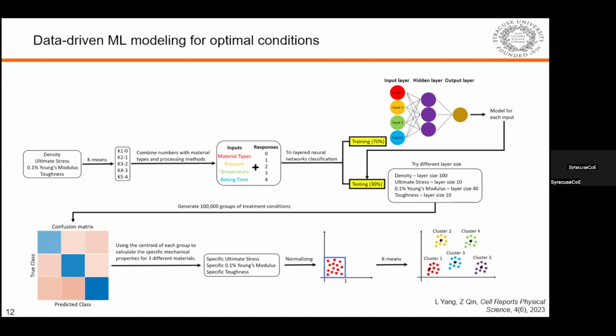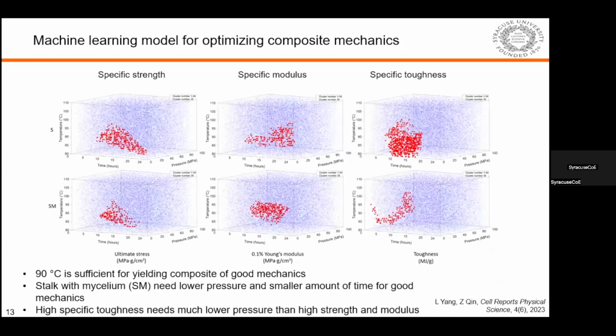So we correlate those processing conditions with the performance of mycelium, and then we build a machine learning model. So it's able to predict what can be the best combination of treatment parameters for strength, for modulus, for toughness. So that's the highlighted region by red color. That's the cluster of the results corresponding to the highest strength, modulus, and toughness. And then we can use the location of those regions to identify the optimal treatment condition for better mechanical performance.